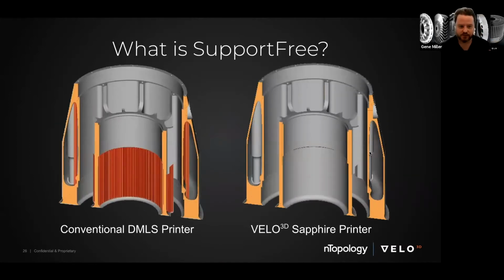So here's a comparison between a conventional DMLS printer supporting scheme versus a Velo3D Sapphire. Everything on the left under 45 degrees has support material added to it. Some of the areas are accessible in the center of this part, but the enclosed volumes that are inaccessible, where there would be support on a conventional system, just don't make sense. You can't get to this after printing, so you're kind of printing garbage. The Velo3D Sapphire printer has no need to put support on these internal volumes. So at the end of the build, all you have to do is remove the powder from these channels, and they're open and free flowing, with no need to add any support material.